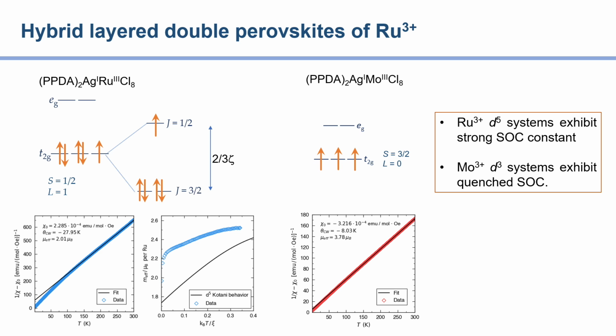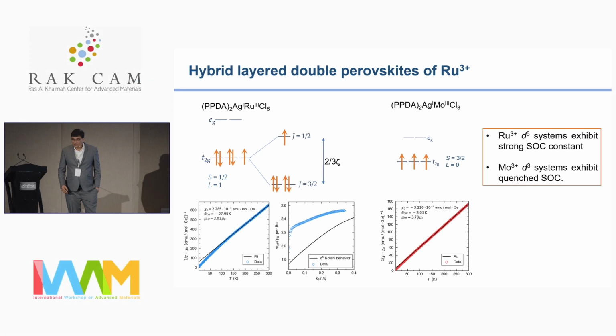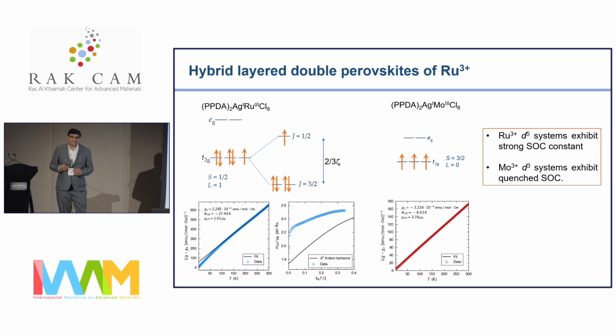And there's a difference in the number of unpaired spins. So here is the J-effective one-half system, and here it is a spin-only system, because L is 0. And this can clearly be seen in the magnetic data analysis. We see the molybdenum system perfectly fits the Curie-Weiss equation, whereas the ruthenium-based system does not, because there's a spin-orbit coupling strength involved, and we see deviation. However, this is still an open question: we do not know why they don't fit and what should be the exact SOC value in the ruthenium-based system. More systems need to be explored.